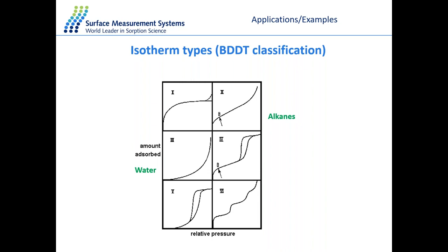There are small variations, but it's one of these 6. Now, if you look at these isotherm plots, which are commonly reported in the literature, the only 2 plots that have a linear section in the lower region, which is called the monolayer region, are type 2 and type 4, because they have this linear section right here. Anything that is non-linear, which is more curved, usually does not describe a monolayer formation and does not allow the calculation of BET surface area.